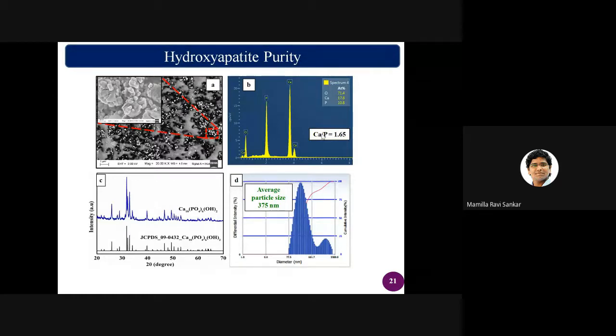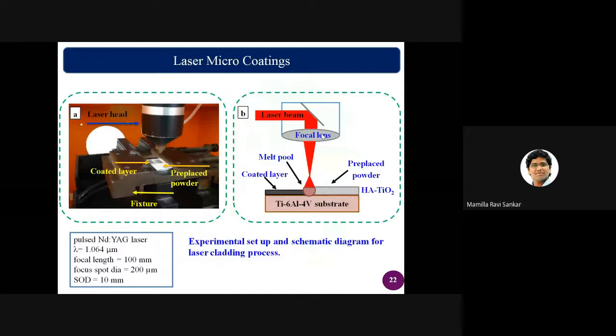Currently, our material has a purity of about 99.56%. That means we can use it in biomedical applications. Initially when we started, it was about 60%, 66% pure, which we could not use at all. So gradually, it took us almost 2.5 years to develop it from the physics scales and other things. Okay, that is one.